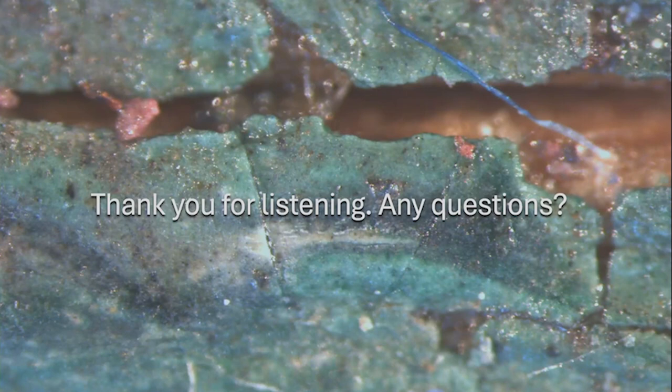That's a great question. As to the first, I was able, through my research, to determine that it was likely an animal hide glue. I didn't conduct analysis, and in the areas of split where glue might have been visible, it's been washed away, which was a good indication that it was something activated by water. So not something waterproof like later plywood production, which used phenol formaldehyde and urea formaldehyde resins, which would not be sensitive to water. In any case, those came into use around 1935, so it would have been the very tail end of our time period. Prior to that, it was almost exclusively animal hide glue, so it was definitely the most likely adhesive used there.